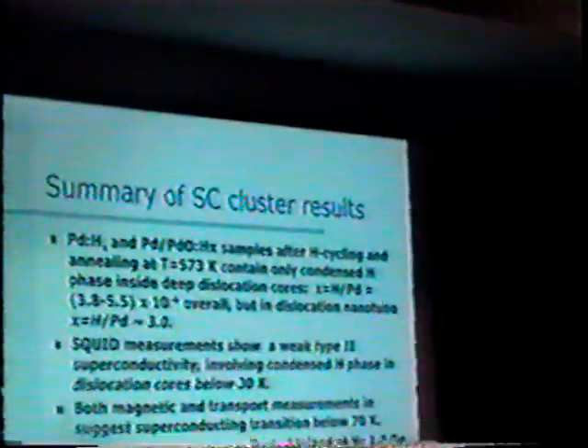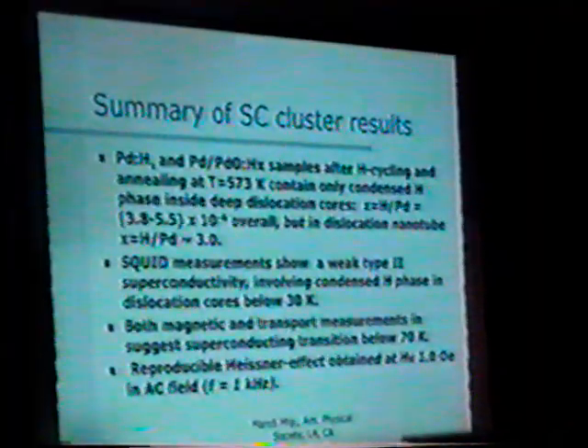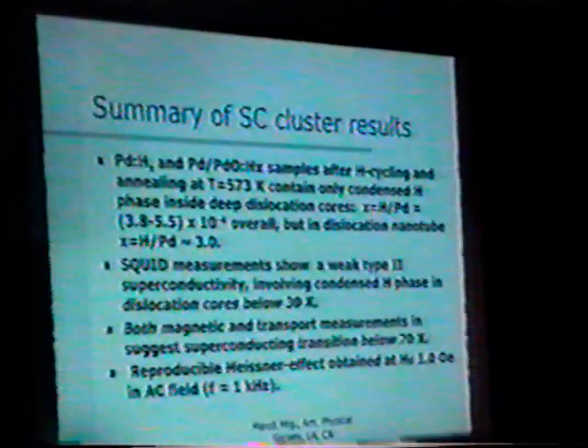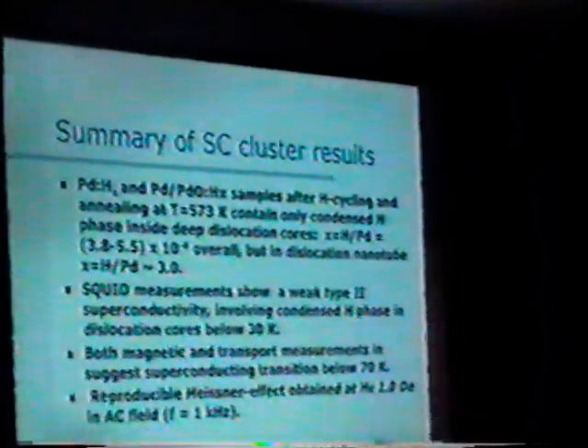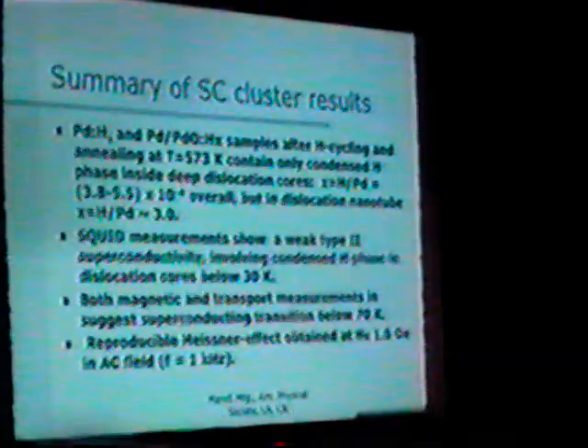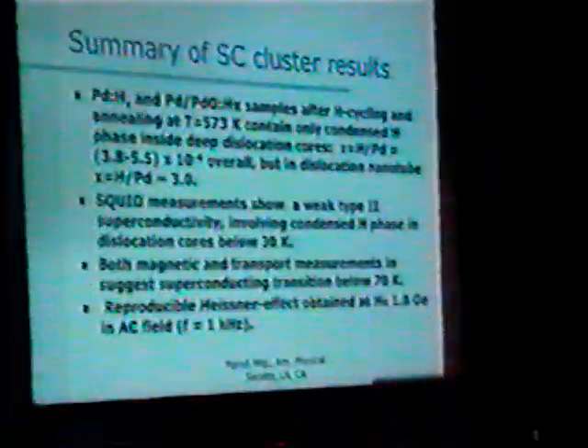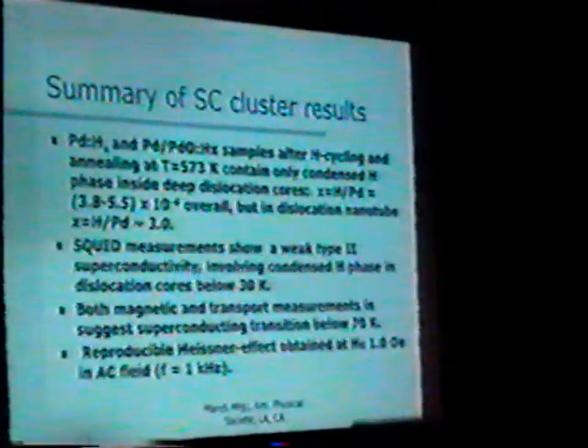Okay, so I'm almost done. PdHx and PdOHx samples after H cycling and annealing at temperature 573 degrees K contain only condensed H phase inside deep dislocation cores. X is the concentration, the amount of H per Pd. And when I talk about full loading, I'm talking about 1 H per Pd. The overall amount is this, but in dislocation nanotubes, it can be as high as 3. And that's what I was saying. Yeah, that's right. They postulate it's a nanotube structure.